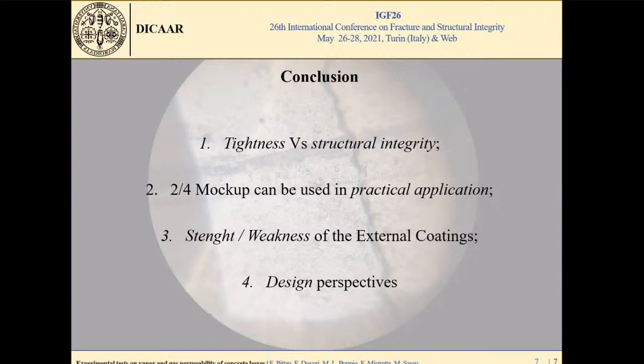And the critical elements are the joints. The joints are critical points that have to be surveyed with care and attention. In the application of the coating, in fact, play a very crucial role the preparedness of the worker and the initial state of the surface of the concrete. So in order to ensure a good performance in time, a periodical check and inspection to measure aging and eventually singular condition of the coating is absolutely suggested.